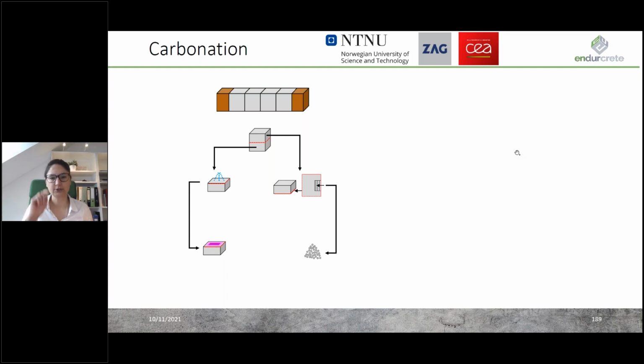And at these various carbonation times, we took blocks out of the carbonation chamber, actually split them, and then on one part, we determined the carbonation depth, as most of you know, with a pH indicator, spraying the surface and reading the carbonation depth, either manually or with image analysis. And then the other part, we profile ground inwards, so we get powders from various steps towards the inner of the sample, and these powders were analyzed with TGA, so we got an idea about the portlandite content and the calcite content at these various steps. So from this part, we got a pretty good idea on the carbonation development over time, because we did that at various carbonation times.